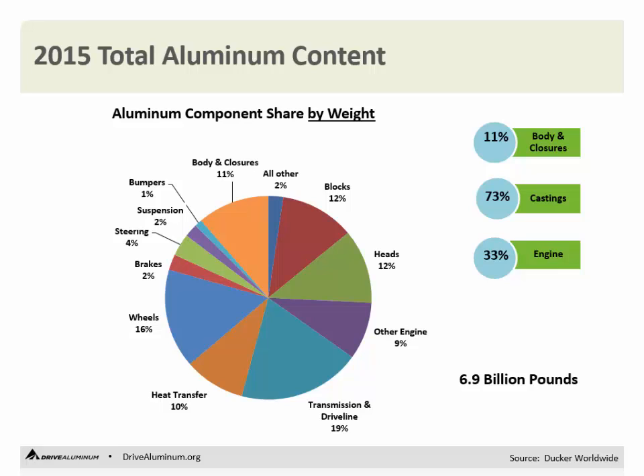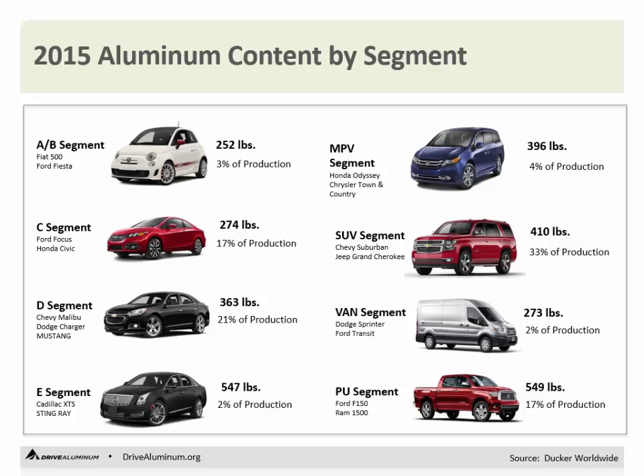Castings will be 73% in 2015. Now that's down from 82% just a few years ago, and typically running well over 80% for castings. And that's not down because castings are down, it's down because sheet and extrusions are up. And the engines are down from roughly 50% to about 33%, again, because of the penetration in body areas.